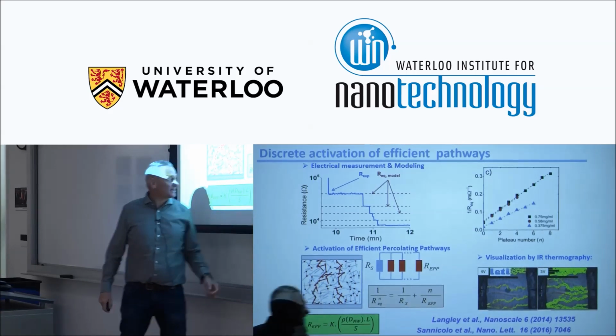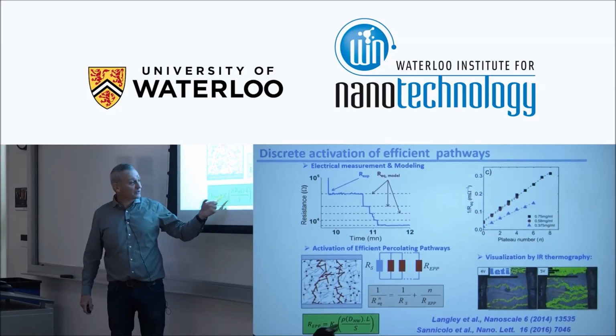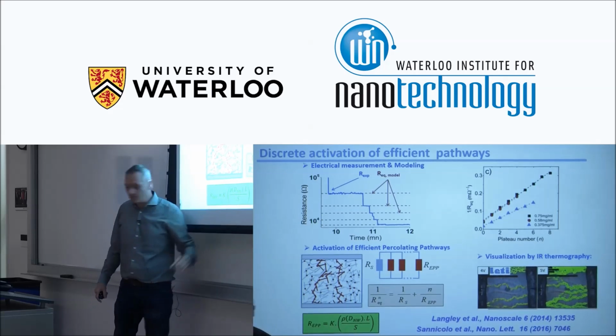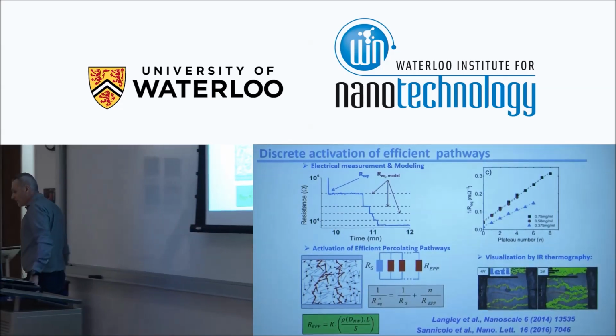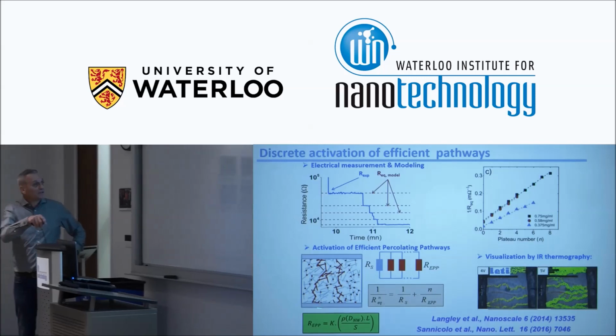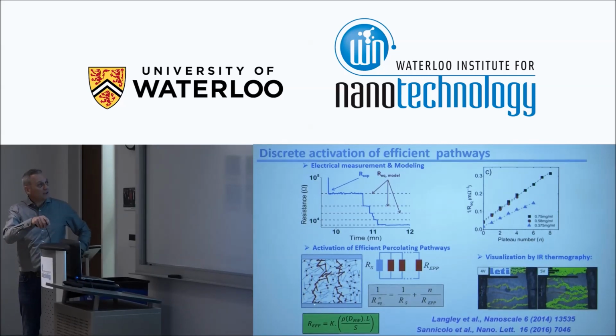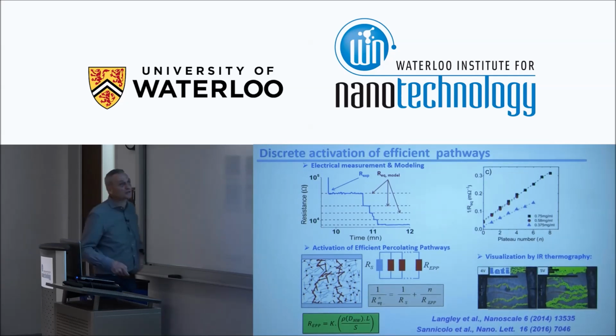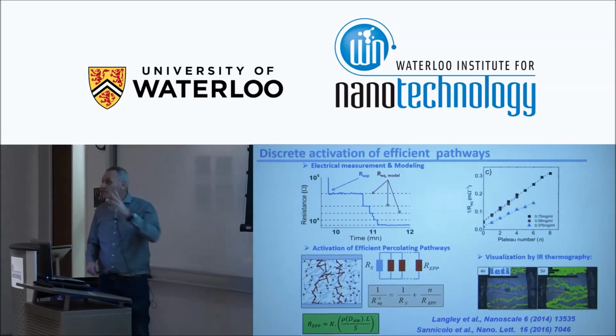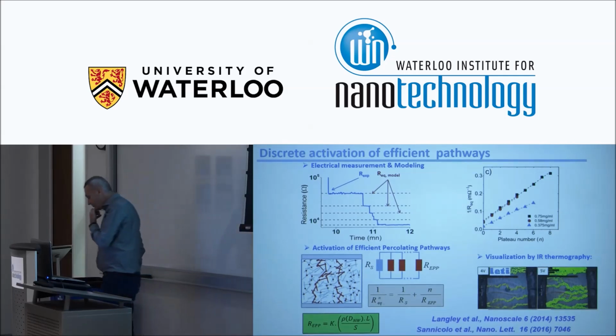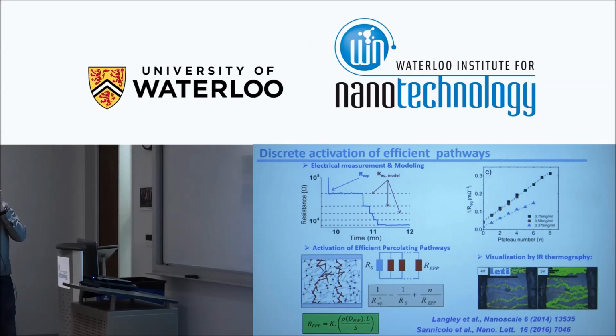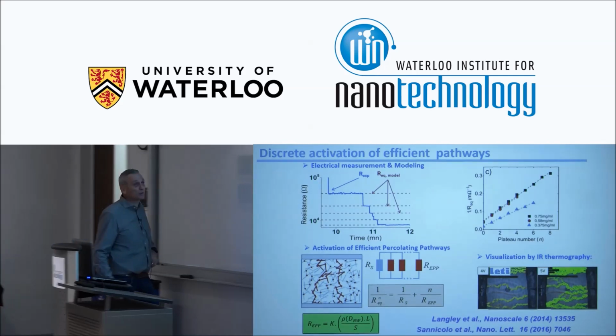calculate this. We can use what we call Pouillet's law, saying that the resistance of a cylinder is the resistivity times the length divided by the surface area. But we have to put a K here, because first it's a bit tortuous, and then as well, we have to cross a lot of junction resistances, which are not zero, so K should be larger than 1. And we found K to be something like 2, 3. But K is our fitting parameter, because we are supposed to know all of the other parameters. So that is what we did, and we published that in Nanoscale in 2014, but we were not able to visualize them,